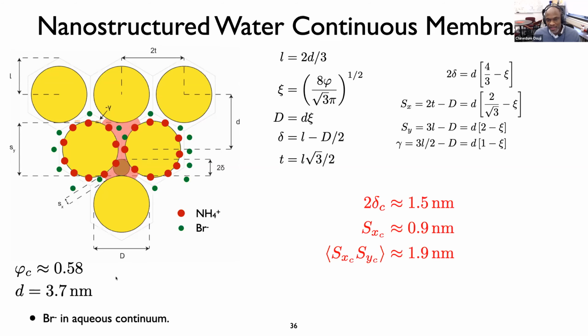Okay, so the two things that we control, of course, are the size of the molecule that we use in making this mesophase and the volume fraction of the molecule that is required to form a mesophase of a certain symmetry. Based on those two things, which reflect themselves in structure characterization by something called the D-spacing here, and the volume fraction of the surfactant in the mesophase, which we use to define this parameter xi, all the relevant dimensions that pertain to transport regulation become accessible to us.